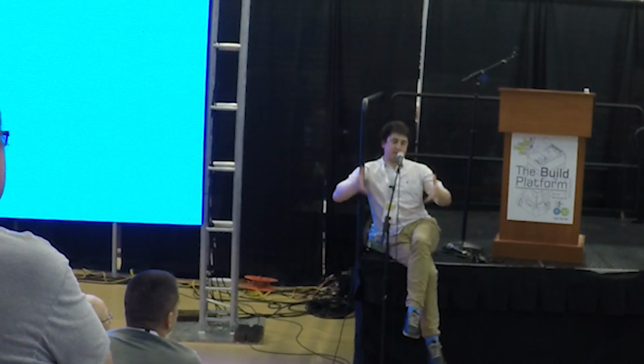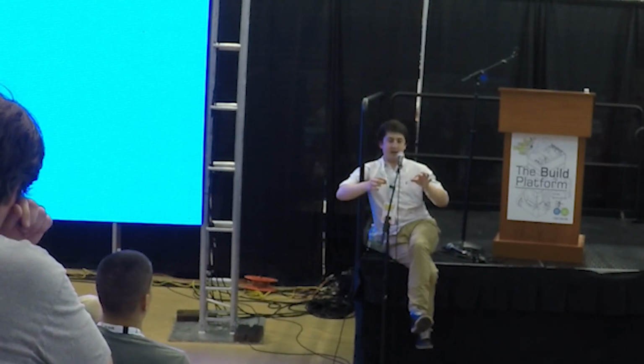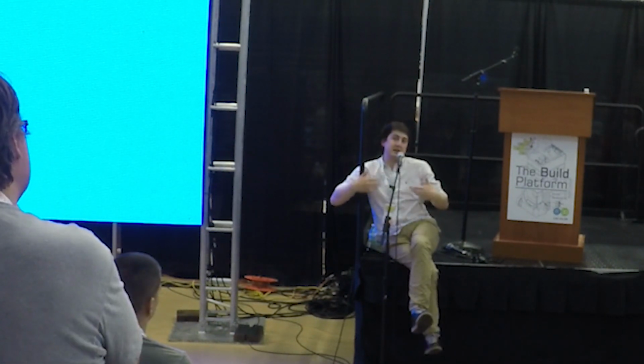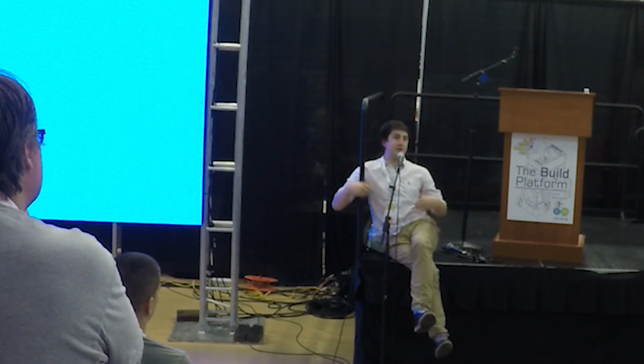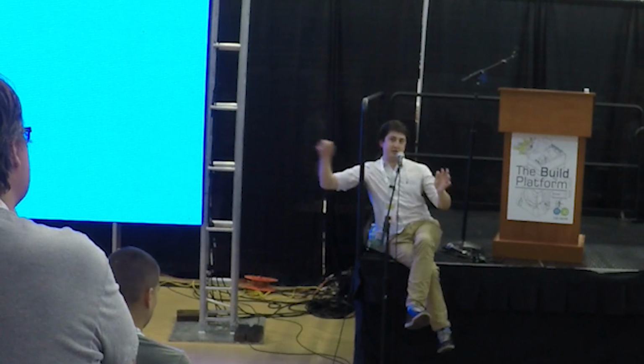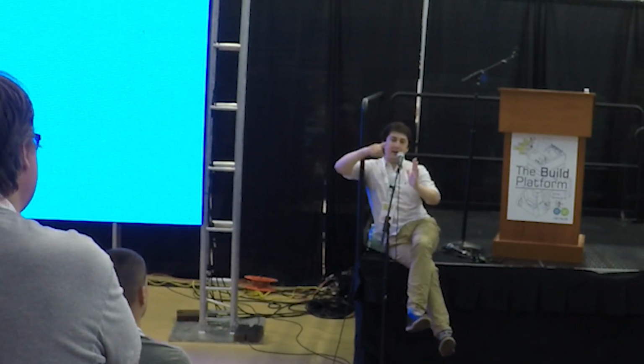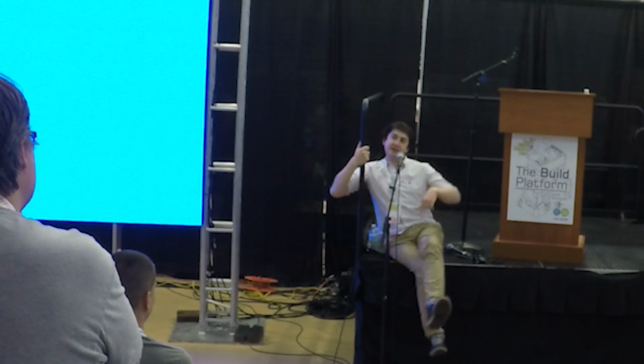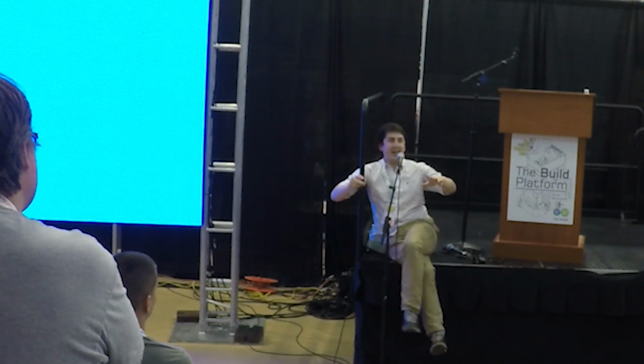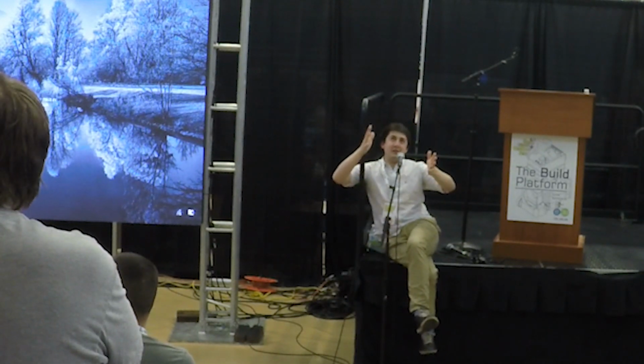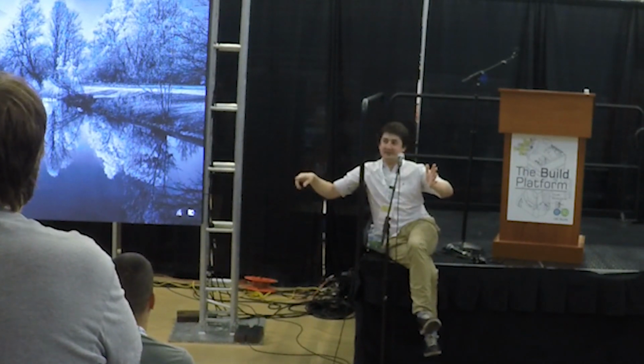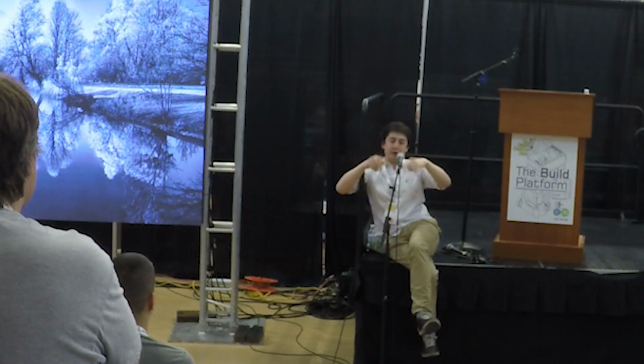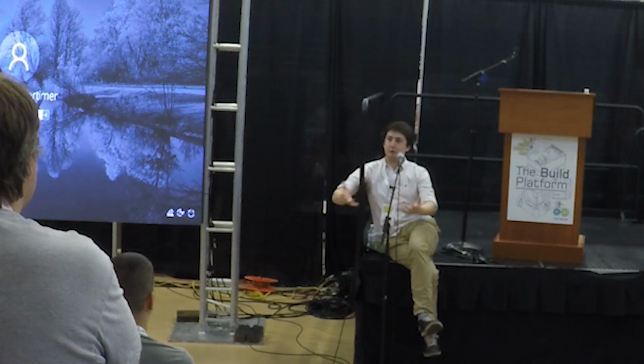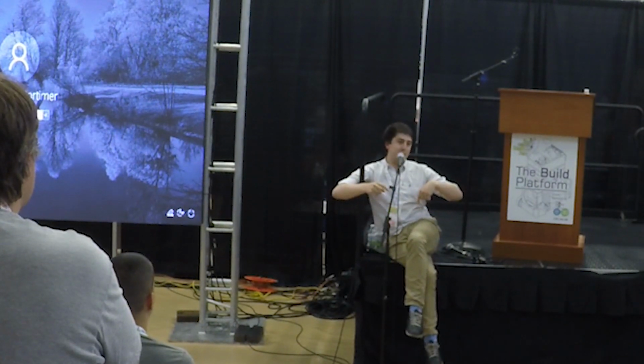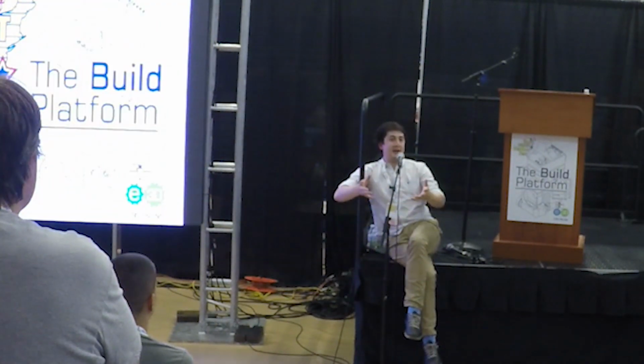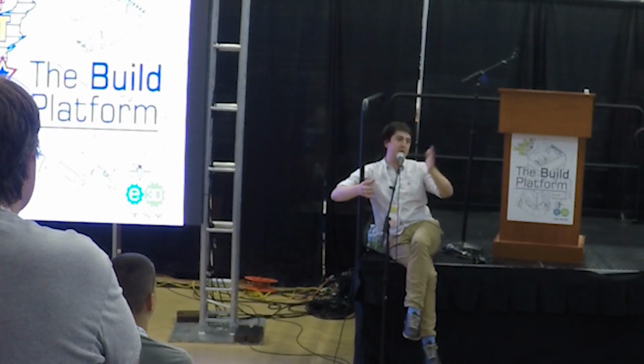We hook up our extruder into this rig and watch the filament move while commanding it to move at constant velocity. You don't actually get a true constant velocity. You get a whole bunch of little piecemeal errors. And so you have this error signal. You take that and you run it through a Fourier transform, right? And so that's really cool. Suddenly you get these peaks come out at different frequencies, and so you can go through. And we had this one big peak, which was causing 80% of the error, and you run that frequency back through the gear train, and it comes out to be exactly on point with the full steps of the motor.